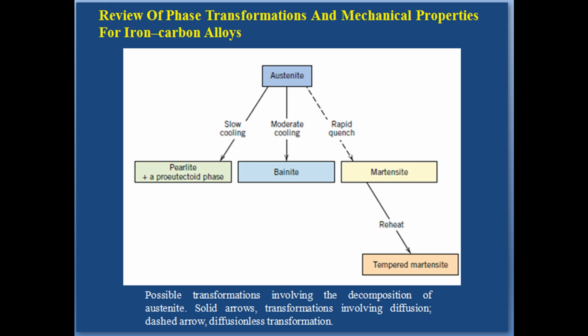Austenite is slightly denser than martensite, and therefore during the phase transformation upon quenching, there is a net volume increase. Consequently, relatively large pieces that are rapidly quenched may crack as a result of internal stresses. This becomes a problem especially when the carbon content is greater than about 0.5 weight percent.